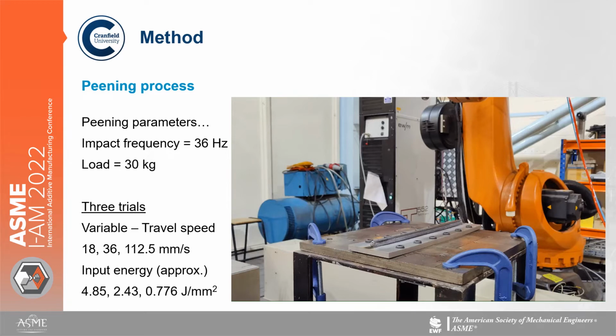So out of 3 trials, we varied the travel speed, which we used 18, 36 and 112.5 millimeters per second travel speed, which was the travel speed of the peening tool over the top of the deposited layers. So that gave us an approximate input energy of 4.85, 2.43 and 0.776 joules per millimeter squared.